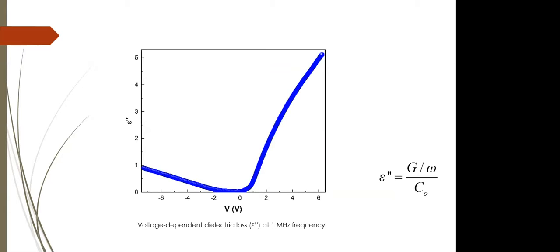This graph shows the variation of dielectric loss epsilon double prime of the sample depending on the voltage. Dielectric loss, we know, is the energy consumed by converting into heat in the material. By using conductance measurements and the equation seen on the right side of the slide, we calculate the dielectric loss values.